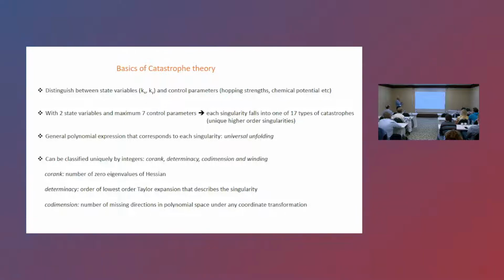We have a general polynomial expression for the energy of the system, if you like, and this is, in that language, universal unfolding. We can forget about that, but an important part is that we can classify uniquely by 4 integers. Winding number, I'll start with the last one. Winding number is, if we go around, how many times we change the sign of the dispersion relation. So when we have holes or electrons, if we go around the point.